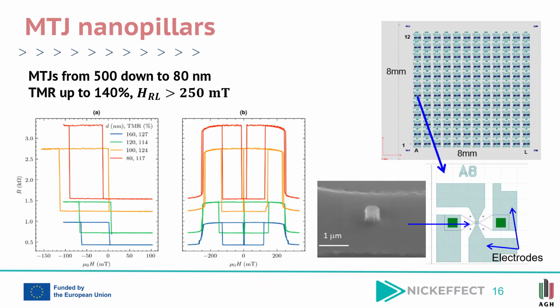after nanopatterning. High TMR values reaching up to 140% were obtained together with reference layer stability fields exceeding 250 millitesla, demonstrating strong stabilization of the optimized SyF RL system even at nanoscale dimensions. These results confirm that the optimized PT-free MTJ stack maintains excellent magnetic and transport properties after device fabrication, and it's suitable for further STT switching and reliability investigations.